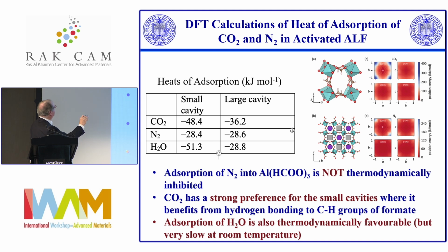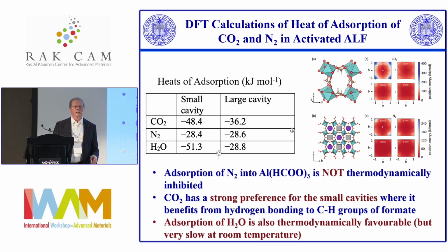So we were able to calculate the heat of adsorption in the small cavity, which is about 48 kilojoules per mole, and the large cavity is about 36. Bearing in mind that most of the CO2 goes in the small cavity, that's in really good agreement with our value of 47 from the experiments. There's no reason why nitrogen shouldn't go in. It's got a reasonable heat of adsorption, but it basically doesn't go in significantly at any temperature. And so this is a kinetic effect. The nitrogen is just ever so slightly bigger than the CO2, and yet the window into the cavity is too small to admit the nitrogen into the cavity.